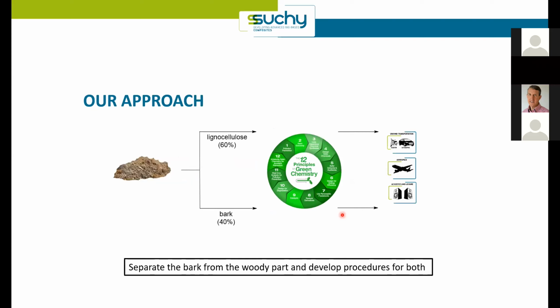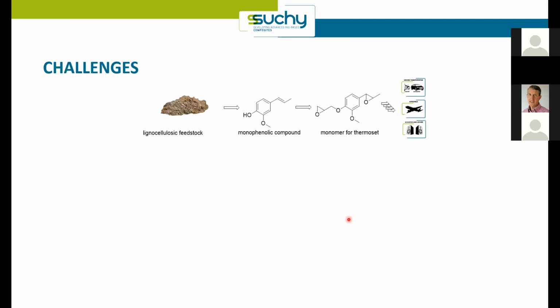So our approach was to use the forest residues and the bark. And in the forest residues, we have both a lot of lignocellulose, that is the wood part, but also bark. And then apply the 12 principles of green chemistry and convert these into these monomers to produce polymers. So I will just give you a first example on how we thought in the beginning and how reality came up during this project, where we have learned a lot actually about sustainability. So we wanted to produce this monophenolic compound that can easily be turned into such a compound that can work as a monomer for polymers.